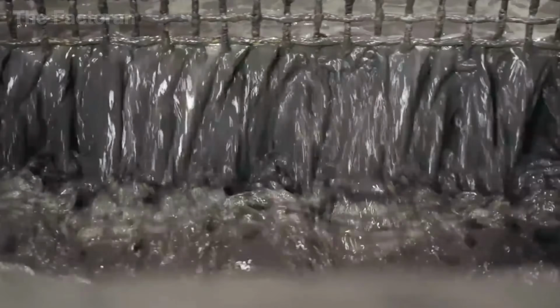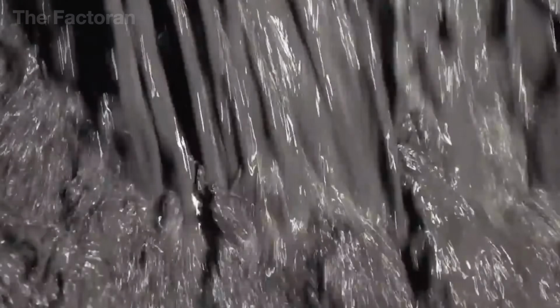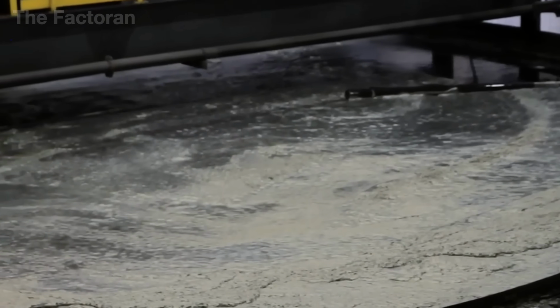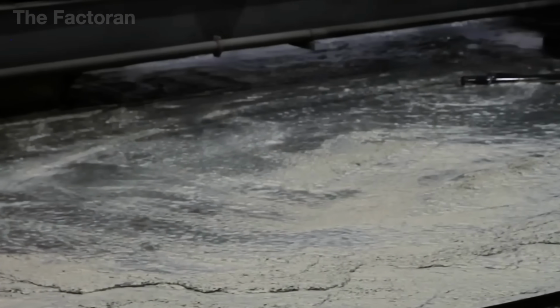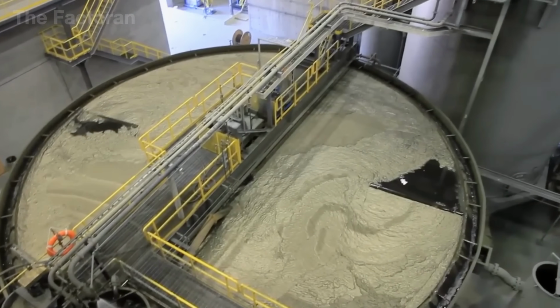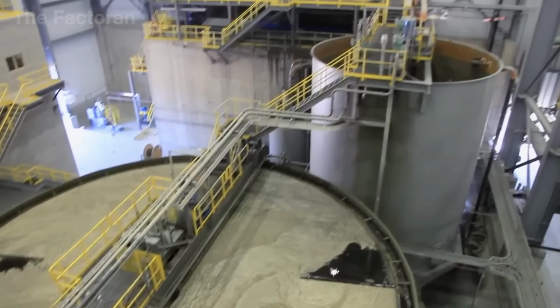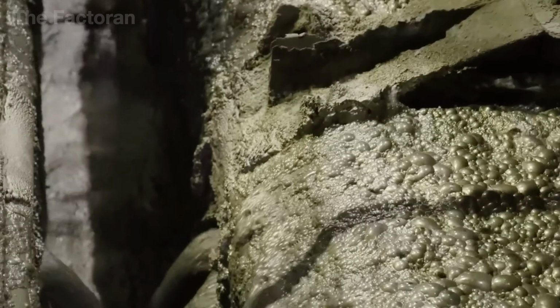This iron-rich froth is carefully skimmed off and collected through multiple cycles, producing a concentrate with Fe content often exceeding 65–67%, more than twice that of the raw ore. It marks a critical turning point where unshaped stone is reborn as a refined resource, fully prepared for the demanding